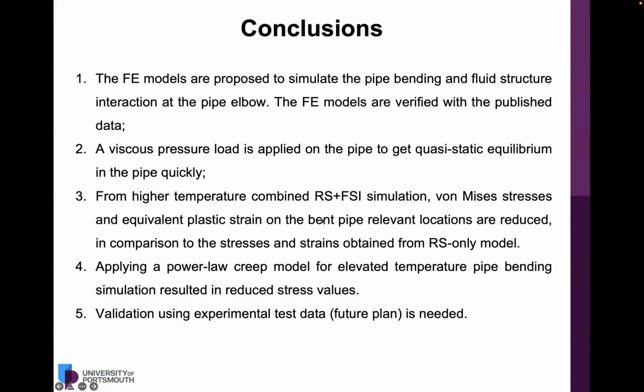From the high temperature combined residual stress and fluid structure interaction simulation, as you can see from previous slides, von Mises stresses and equivalent plastic strain on the bend pipe relevant locations are reduced in comparison to the stresses and strains obtained from the residual stress only model. And the power law creep model for elevated temperature pipe bending simulation resulted in much reduced stress value.